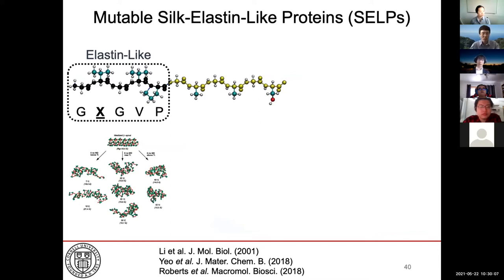Now, elastin-like peptides are composed of GXGVP amino acid repeats, as shown over here. And this is derived from the hydrophobic domain of a protein called tropoelastin. At low temperatures, elastin-like peptides are soluble in aqueous solution, but as the temperature is raised above a transition temperature, they become insoluble and they will start to aggregate. And this process is typically reversible so that subsequent cooling will actually resolubilize the elastin-like peptide.